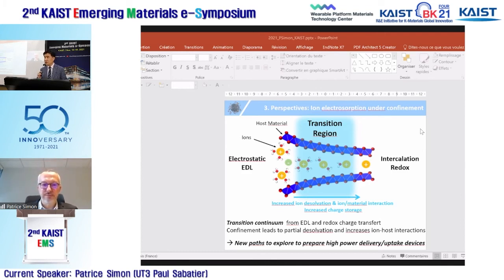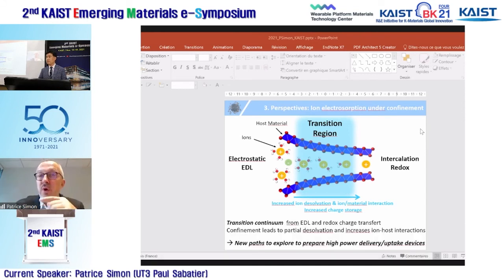Thank you. The third question, thank you for the great presentation, Professor Simon. What is the sensitivity of the EQCM in terms of the minimum unit of mass that can be detected? Yes, sorry, I did not give a lot of details because it was kind of short, but this is typically a few nanograms. It's like a QCM, and this is the beauty of the EQCM, that you can really track what happens at the surface of your electrode. And you saw not only for high surface area carbon, because when you put a few micrograms of porous carbon you have a high surface, but if you take single layer graphene, then you can already measure weight change. So this is super sensitive, a few nanograms.